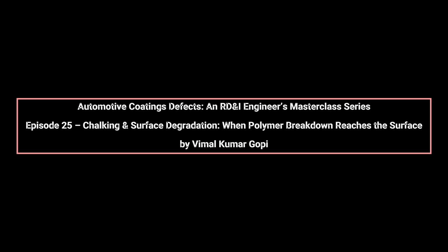The reason chalking appears late in the life cycle is because clear coats are designed to sacrifice themselves. UV absorbers and HALS slow degradation, but they are gradually consumed. Once these protective additives are depleted near the surface, UV energy penetrates deeper and accelerates polymer breakdown. At this stage, gloss has already dropped significantly, and surface roughness has increased. Chalking is closely linked to gloss loss, but represents a more advanced failure.